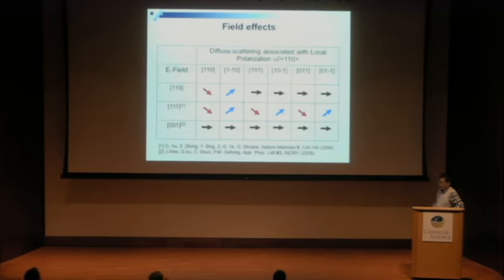And here is a summary of the field effect in this system with different kinds of field. Here, we list 6 diffuse scatterings associated with 6 different local polarizations along the 110 type directions. We show the 110 field will suppress the diffuse scattering coming from 110 polarization and enhance the diffuse scattering from polarization along the 1-10 direction, and have no effect on the other 4. And we know the 111 field will enhance 3 kinds of diffuse scattering and suppress the other 3. And the 001 field has no effect on any of the 6 types of diffuse scattering.